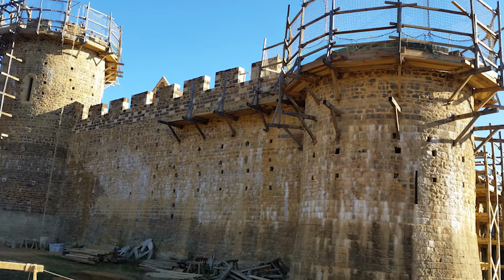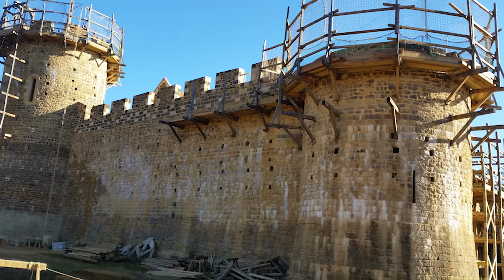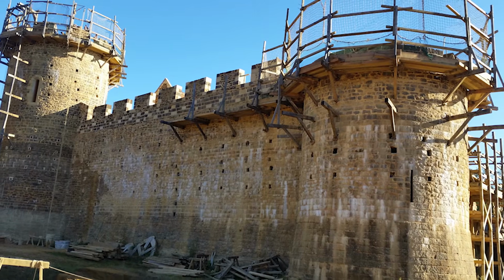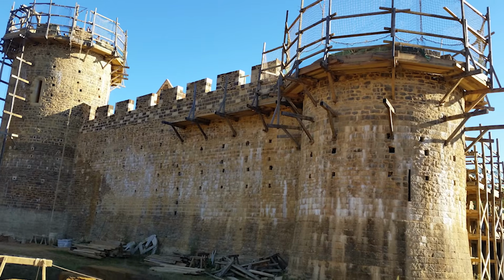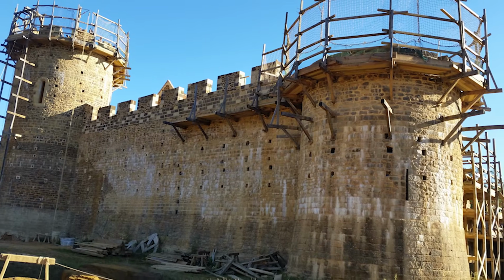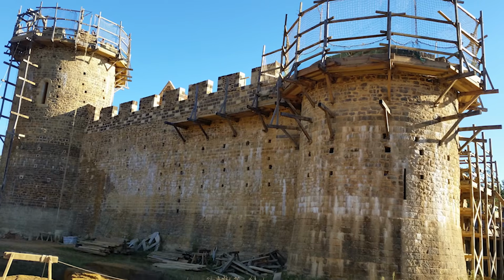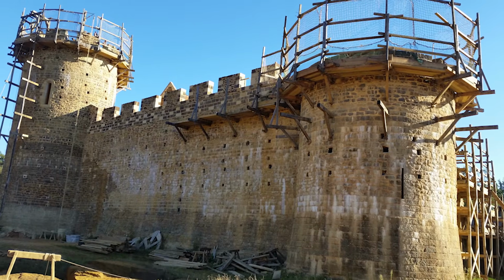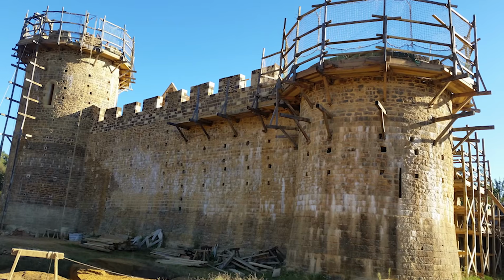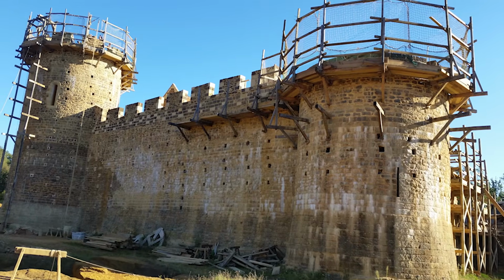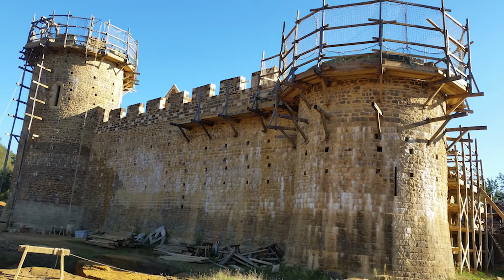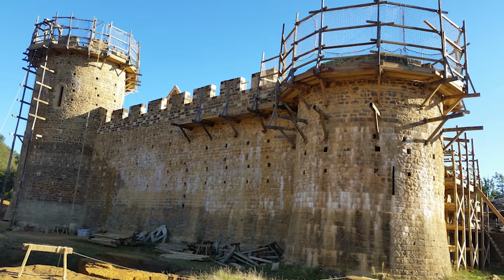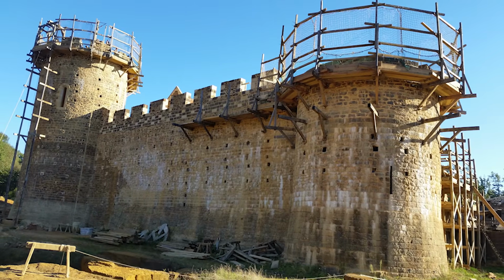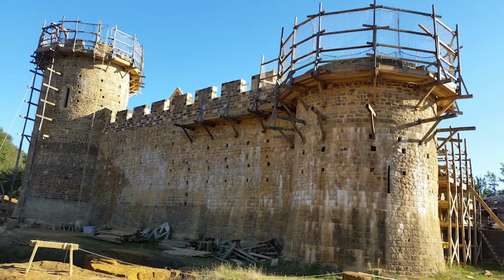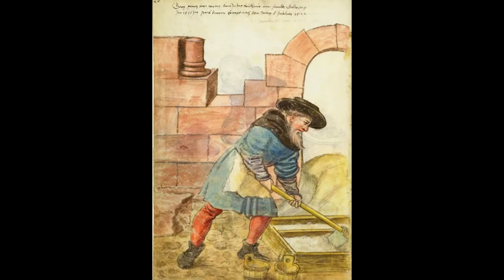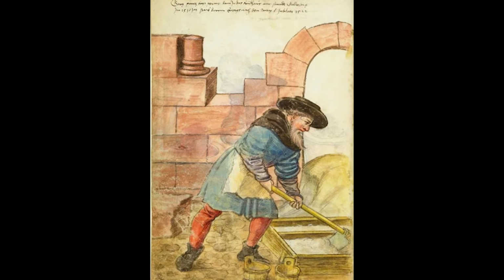The medieval approach to joint design reflected sophisticated understanding of how mortar and stone interact over time. Masons deliberately recessed their mortar joints 3 to 5 millimeters below the stone surface, a technique called weathering that allowed rain to run off without pooling in the joints. This recessed profile also meant that when repointing became necessary after decades or centuries, masons could remove weathered mortar without damaging the stone. Modern flush joint pointing looks neater initially, but creates ledges where water can collect and freeze, while making future repairs more difficult and expensive.